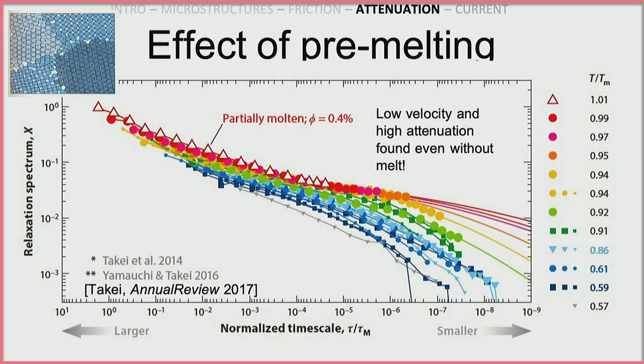It's disorder, right? And so if you've got this tight crystalline material right next to each other, the hotter the temperature, these atoms start breaking apart, and you've got this disorder in the grain boundary. It's not true melt yet, but it's this increase in disorder that increases and increases as you approach melting, and that disorder seems to facilitate diffusion when it's experiencing a periodic stress.